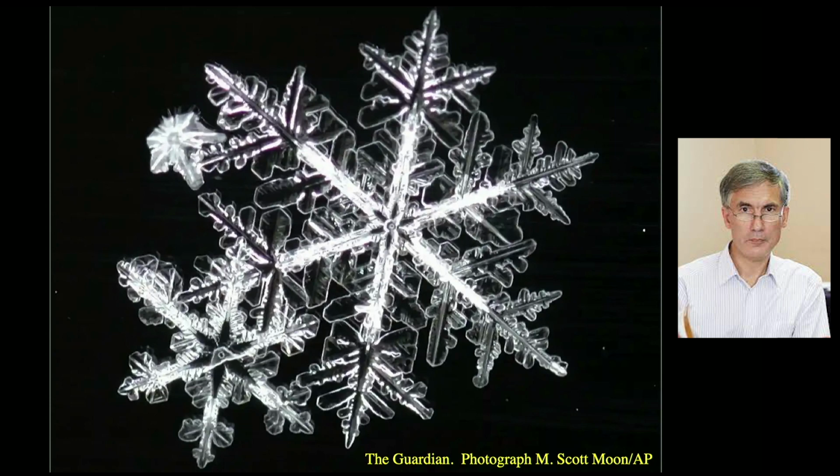So that's the diffusion length, probably millimeter to few millimeter scale. The capillary length is down a few nanometers. The geometric mean of that gets you into the 100 micron range. So the smallest scale of perturbations, you should be seeing around 100 microns versus a few millimeters. So very typical.